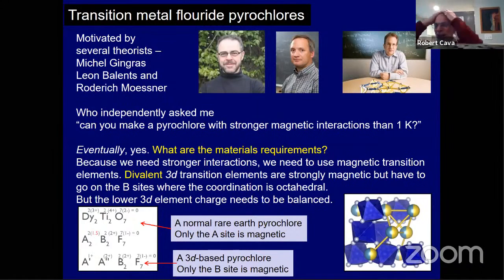And then you have to get charge balance. You have to be able to make something where you balance the charge. So if you have a divalent transition element, which has a high magnetic moment, then you can't make a pyrochlore anymore out of oxygen. You have to use fluorine. And so that's the principle. The trick is, how do you do it?